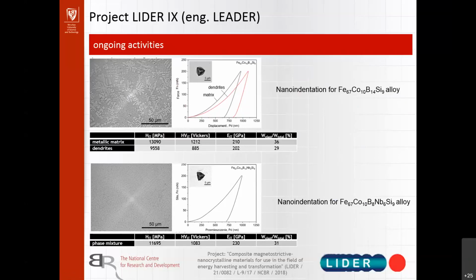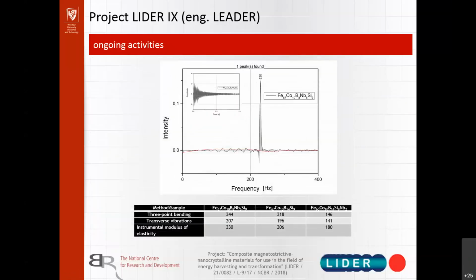After that, we also checked the elastic modulus for other materials with 3 different methods. You can see that we were using the mechanical method, so 3-point bending, the acoustic or vibration method, so transverse vibrations, and, as I previously mentioned, the instrumental modulus of elasticity. We can see that the instrumental modulus of elasticity and 3-point bending are very similar to each other, and with transverse vibrations the elastic modulus is not as big as in the previous methods. However, we may say that they are very similar to each other.